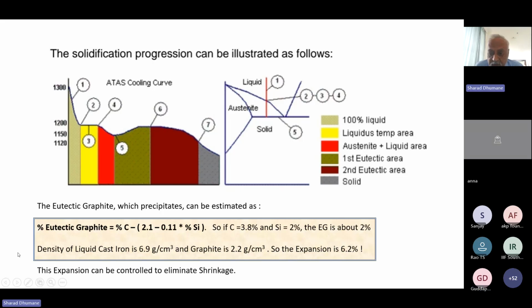Okay. So why is this amount of eutectic graphite important? Because when graphite was dissolved in liquid cast iron, the density of cast iron is 6.9 grams per cubic centimeter. The density of graphite is 2.2 grams per cubic centimeter. So when the graphite comes out, the density of liquid cast iron slightly increases, but the graphite, since its density is very low, is going to expand. 2% of graphite, when it comes out, expands the volume of the liquid.